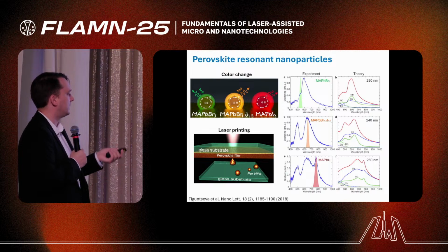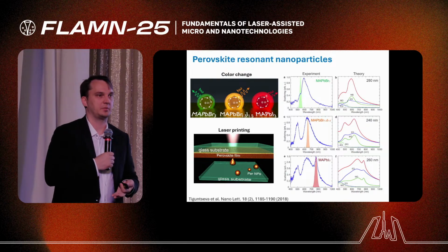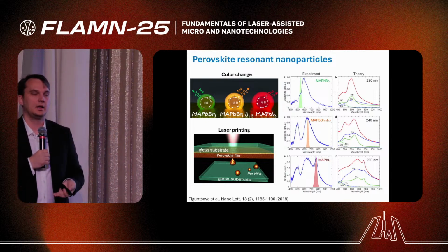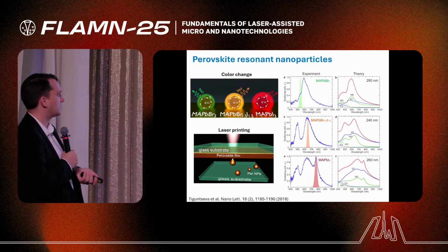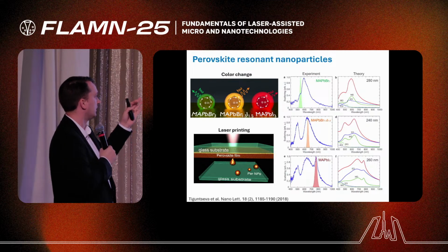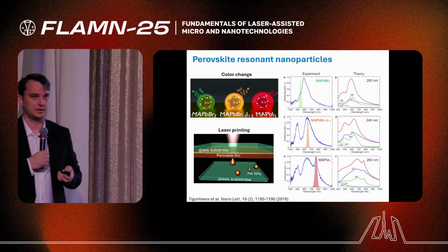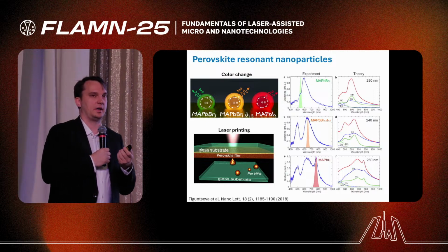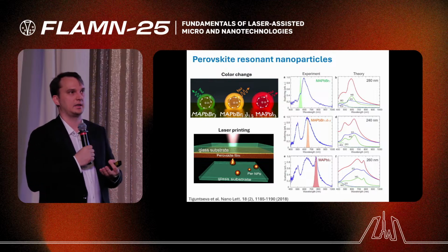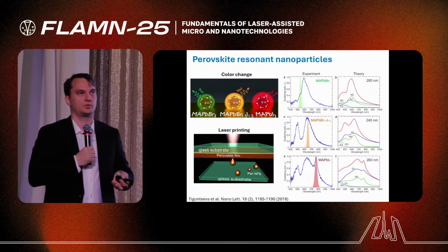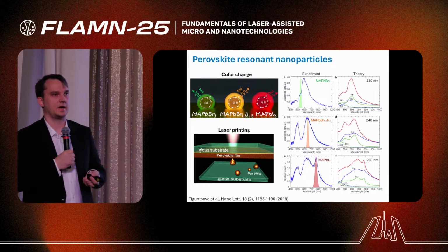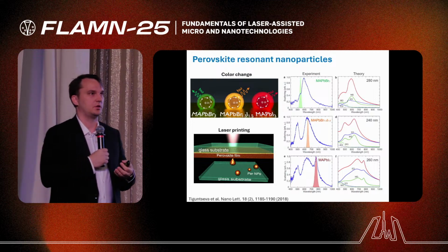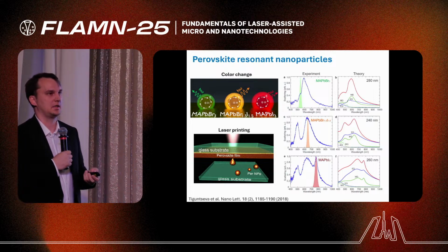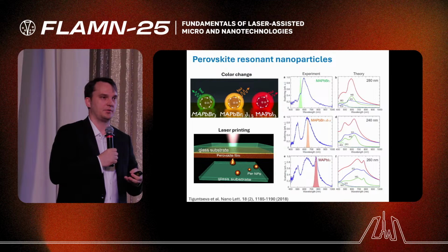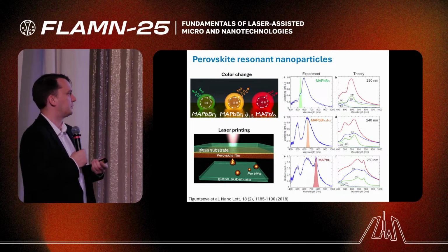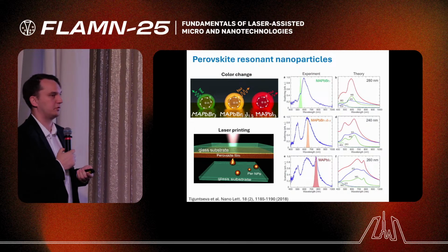One year later we applied laser ablation in air and deposition, like printing on a substrate, for perovskites of different composition, which emit light in the red range and the green range. Interestingly, if you want to apply such a technique to a light-emitting semiconductor, let's say gallium arsenide or indium phosphide or any kind of III-V semiconductors, after such laser ablation they wouldn't emit light efficiently because we generate a lot of defects. But because perovskite is a defect-tolerant material, direct ablation doesn't destroy perovskite and it's not so harmful for photoluminescence.